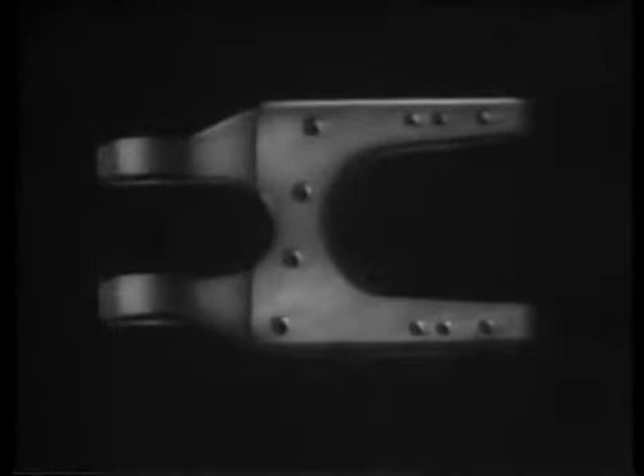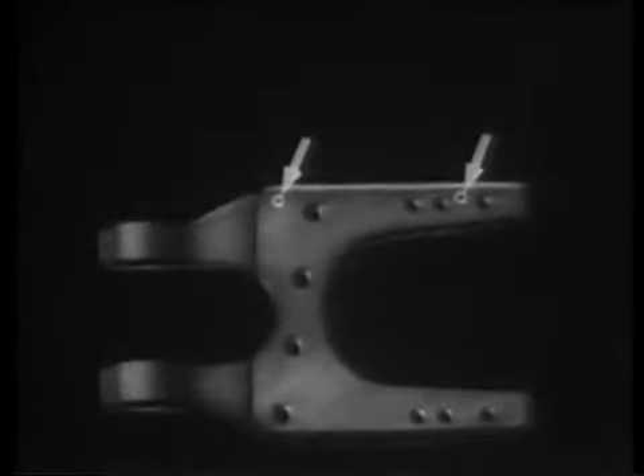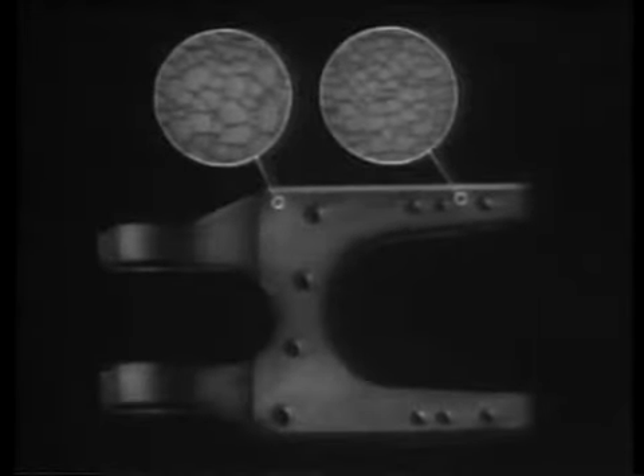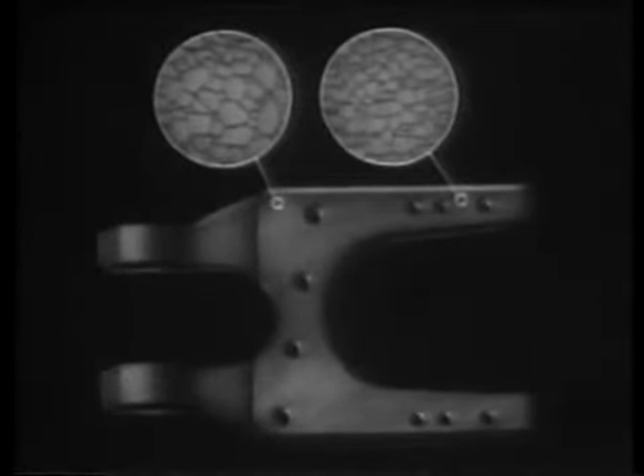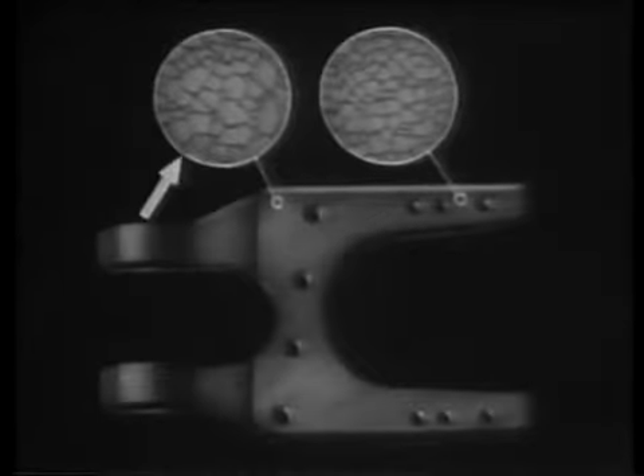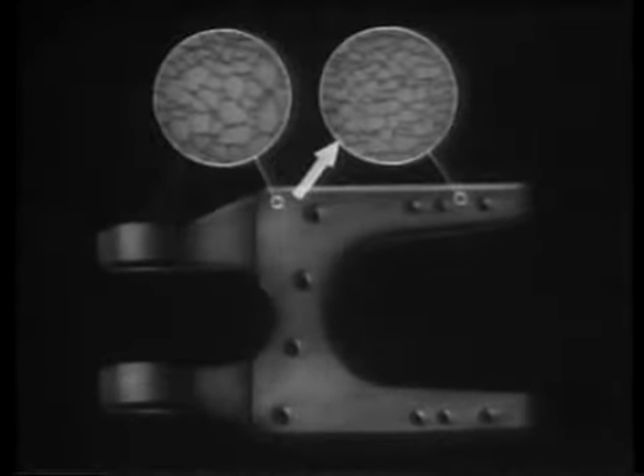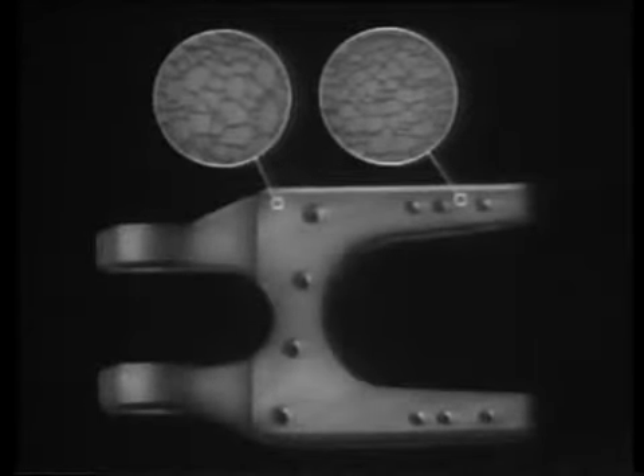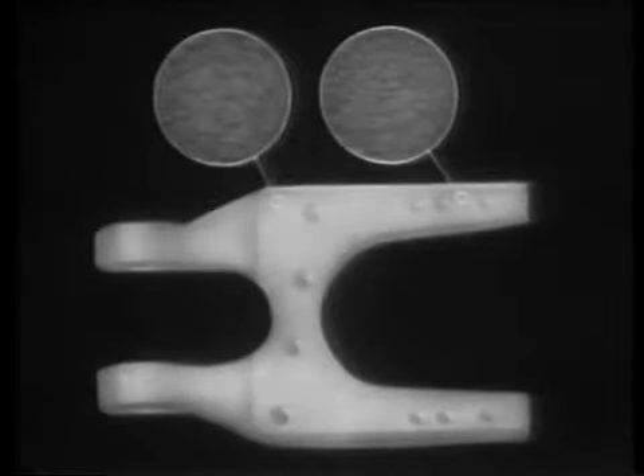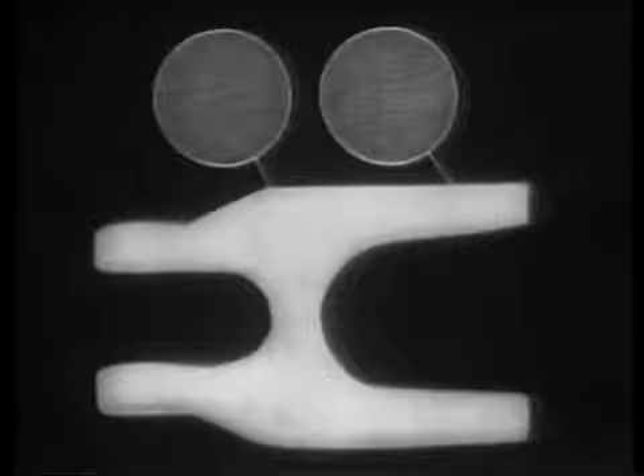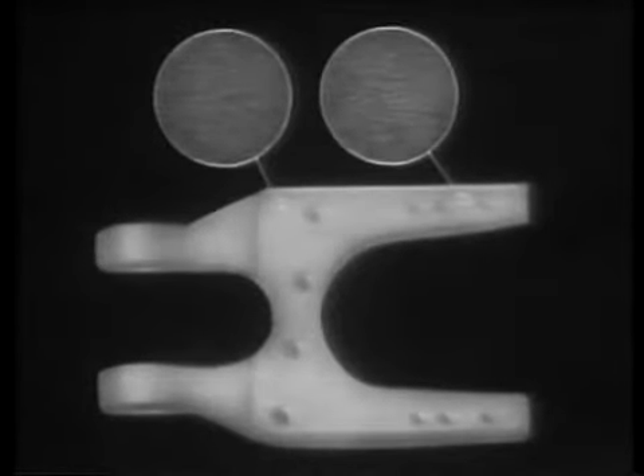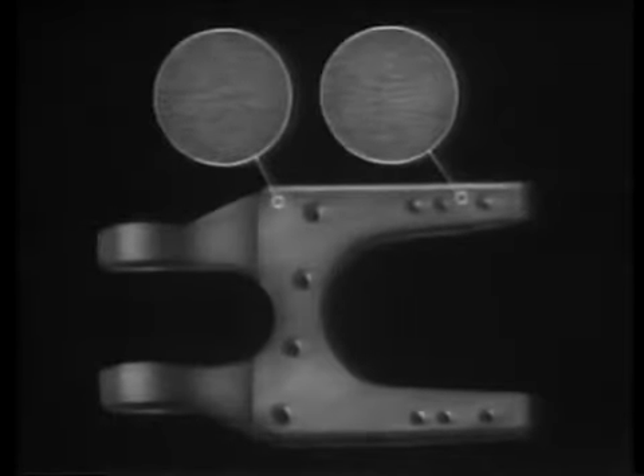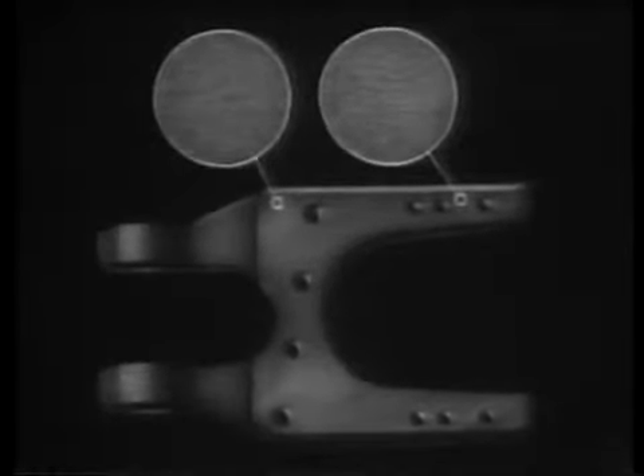Here is what happens during the normalizing process. Before normalizing, the crystal structure at these 2 points looks something like this, coarse and non-uniform. Notice the considerable difference in the size of the individual crystals. Furthermore, the crystals in the wide section are relatively larger than those in the narrow section. As the part is heated to high temperature in the furnace, its varied crystal structure changes to one which is uniform throughout. Normalizing reduces the size of all the crystals. The result, a uniform, fine-grained structure.